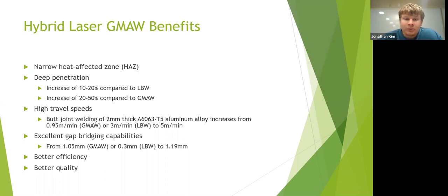Also, one of the things that the laser beam welding process alone was very poor at was the bridge gapping capabilities, at 0.3 millimeters. The gas metal arc welding process was a lot higher at 1.05 millimeters, but whenever you combine them, you can actually get up to 1.19 millimeters of bridge gapping. This is very useful for bridging large gaps.